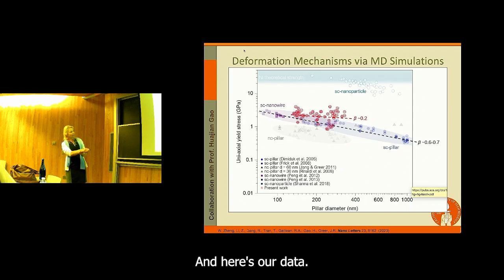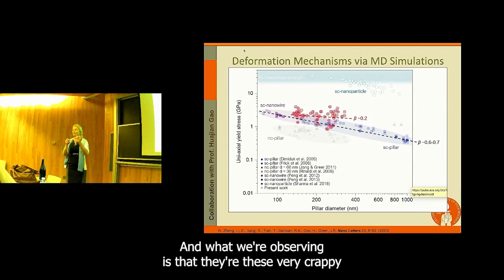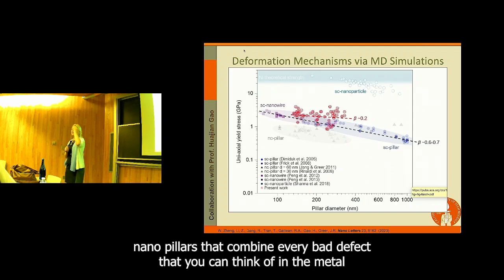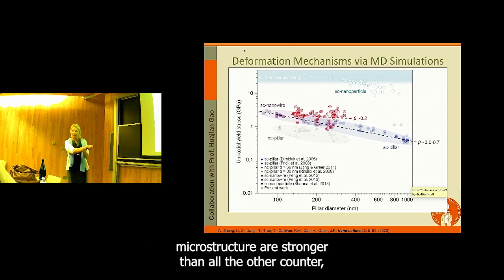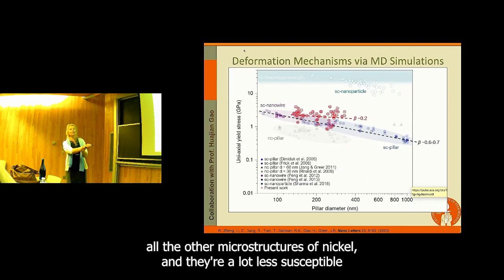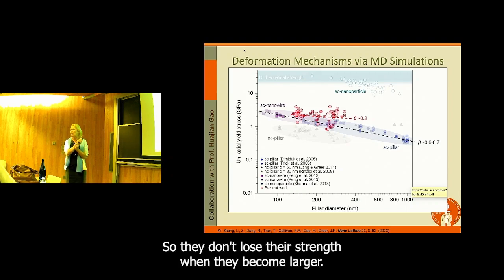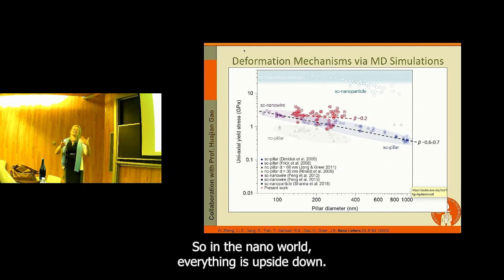And here's our data. And what we're observing is that these very crappy nanopillars that combine every bad defect that you can think of in the metal microstructure are stronger than all the other microstructures of nickel, and they're a lot less susceptible to the size effect. So they don't lose their strength when they become larger. So in the nano world, everything is upside down.